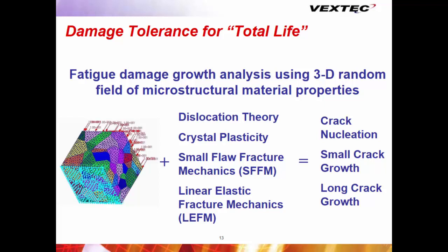The difference is that this crystal plasticity happens over a single grain. It hits a grain boundary. Okay, it's going to get pinned at that grain boundary, but then it's going to go on to the next grain boundary and the next grain boundary, and that happens over and over. And then there's small flaw fracture mechanics. So in a nickel alloy, you might define your initial crack as when it busts through the first grain boundary. That's your initial crack size. So you've got these very, very small cracks, but you've got to use small flaw fracture mechanics to get those to grow. And finally, you get to linear elastic fracture mechanics.